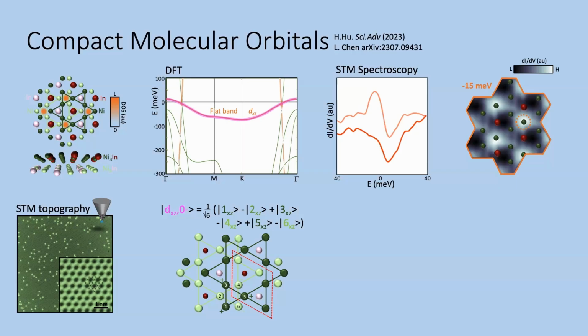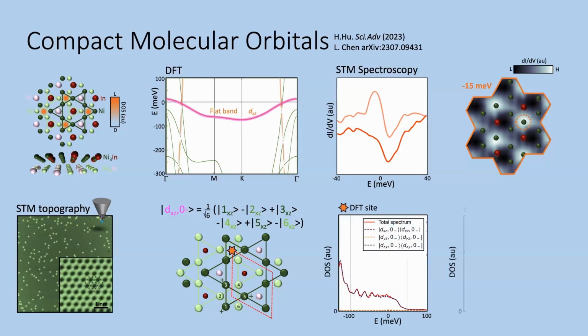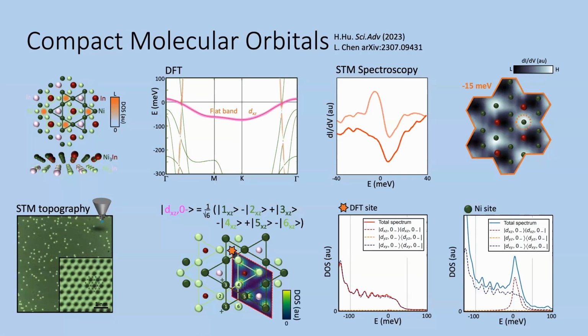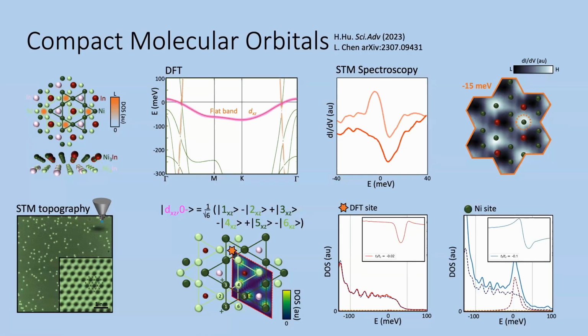And this particular superposition produces what you see in the magenta line. So this is exactly the degree of freedom that produces the flat band. And as they calculated, I'll go quickly, it is localized exactly on the nickel atoms, as we see in calculation. And when they calculate the tunneling spectra on the nickel side and off the nickel side, they see exactly the dip and funnel-like line shape, the peak-dip structure that we see in experiment.